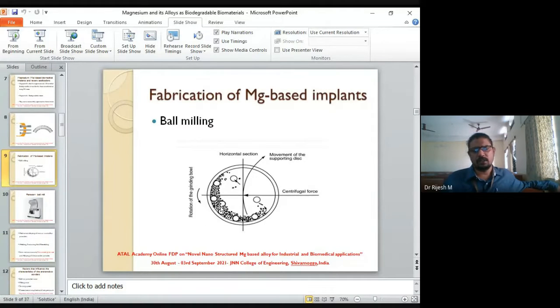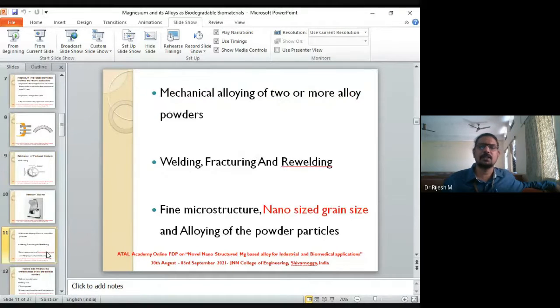The individual powders will become smaller and smaller. Not only that, one powder will actually collide with another powder. There's a temperature rise and you expect diffusion to take place. And such alloys that have been formed not by melting, pouring and solidification, but by diffusion of two solid powders, we call a mechanical alloy. So if you're going for two or more powders, it is basically a mechanical alloy.